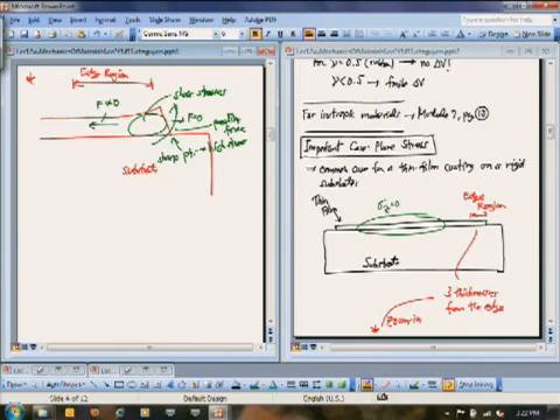And this can happen. It does happen definitely if you etch this film and actually create a patterned film like this, so you can actually have an edge. But it can even happen with films that are not patterned, like nitride films that are deposited too thick over a substrate. First of all, the stress could be very large within the center of that film. You can then get a crack in that film. Now that crack creates this edge condition, and now everything comes up. So this is one way you can have films that curl up even before you release these structures. They're just delaminating from the substrate. So this peeling force will delaminate the film from the substrate. That's an effect we'll talk about later on in more detail.